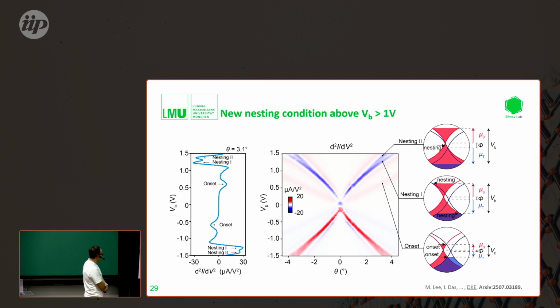And basically, to highlight that only a small nonlinearity can give us such features, this is just a cartoon picture: if we assume that the bands are not entirely parallel, if we assume some small nonlinearity, then instead of one extended nesting condition, we actually get kissing points. We get 2 kissing points where the bands run in parallel, but of course they don't run in parallel over the entire K-space.